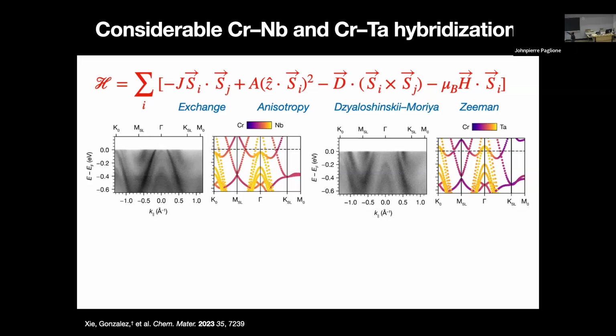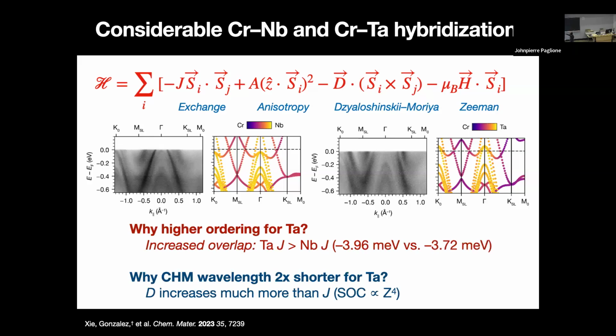Whereas here we have extensive hybridization, which is perhaps in the end not too surprising, between the chromium and the host lattice. And so indeed, we can then ask, well, why is the ordering temperature higher for tantalum? Well, it turns out that it is the increased overlap. So we should probably think more about a superexchange type interaction, which has to do with how the ligands, the tantalum, sulfur, chromium interactions, and the nature of that orbital overlap. That increased overlap is what gives rise to the higher ordering temperatures, and not simply the size of that Fermi wave vector.